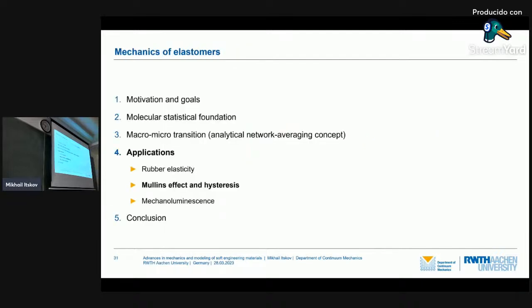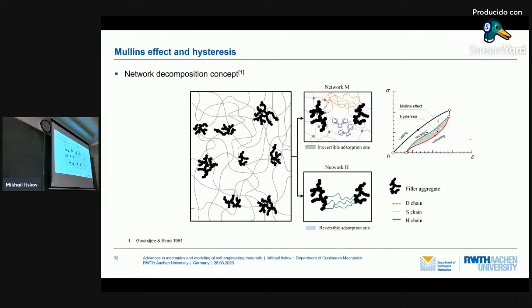Let me now focus on the Mullins effect. The problem is that the Mullins effect is irreversible, which means that if you loaded the material, it was already damaged, and we made an experiment: we left the specimens for 1 week, and after 2 weeks we measured it again, and we realized this material is still damaged. So it is irreversible. It is damaged once and almost forever.